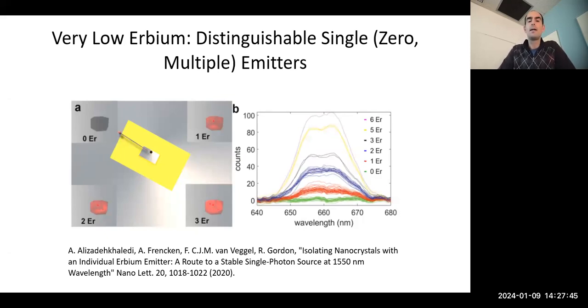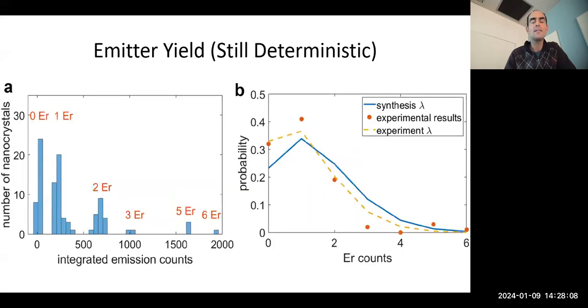And what we observed is discrete levels in the amount of emission. A nanocrystal with no erbium emitters would have basically no emission. If it had 1 erbium, it would have a higher emission. 2 erbiums would be more, 3 would be more, 4 would be more, etc. So doing statistics on this, we can figure out the distribution of the number of emitters in each nanocrystal, and it follows a roughly Poissonian distribution.